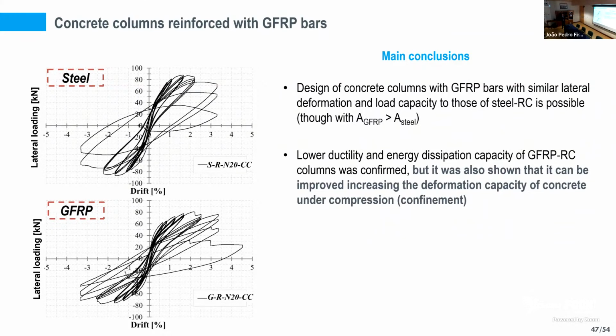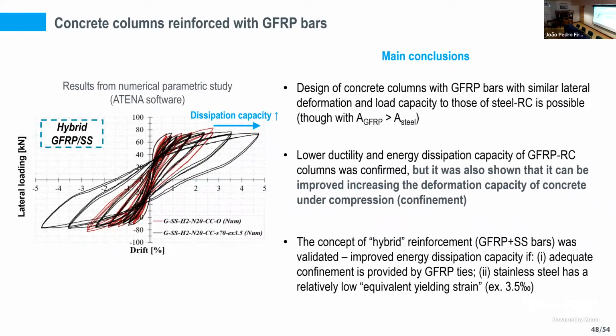this low ductility can be improved if we increase the deformation capacity of the concrete under compression, and we can do this by improving the confinement. And regarding the combination of longitudinal GFRP bars with stainless steel bars, we confirmed that the concept can work. So we confirmed that we can actually increase the energy dissipation capacity by introducing stainless steel rebars combined with the GFRP ones.